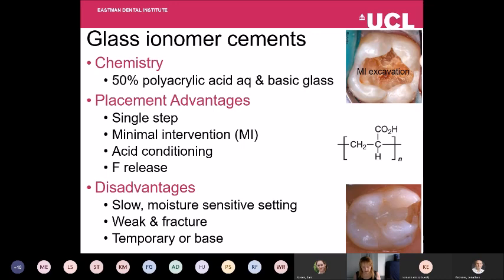Disadvantages of the GICs: they have a slow setting reaction that is moisture sensitive. But the biggest problem is they tend to be weak and you can get fracture of the restoration. So usually glass ionomer cements are considered as a temporary or a base restoration material, so they can be placed underneath, for example, another composite.